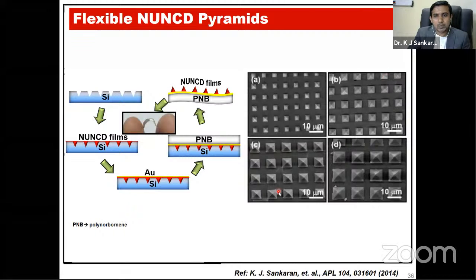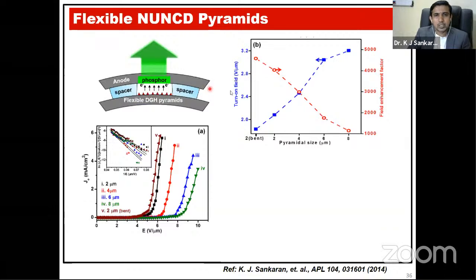These are the SEM images, which show very clearly the diamond pyramids placed on the polynorbornene material with the interlayer of gold. This gold is useful for electron conduction between the pyramids. Then we measured the field electron emission properties of these flexible NUNCD pyramids in a bending way, and you can see that for the flexible DGH pyramids, we achieved a low turn-on field as well as a high field enhancement factor.